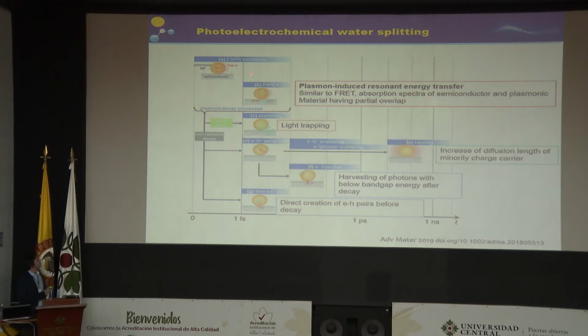And so when we shine the light, we concentrate light close to the semiconductor. For example, we can increase the efficiency of our device by using resonant excitation between the plasmon and the band gap of the semiconductor. So we can use the scattering coming from the particles in the plasmonic materials to enhance the rate of interband transition in the semiconductor. And so we, of course, achieve much higher current, so much higher efficiency in our devices.